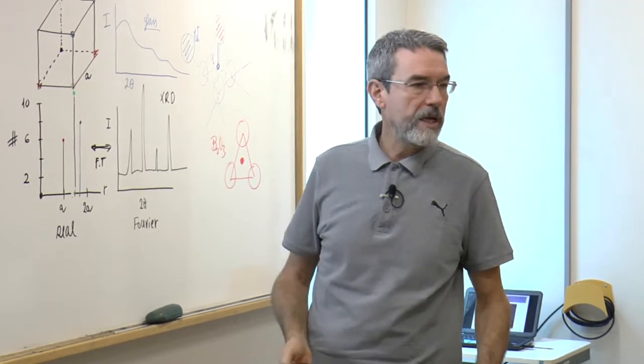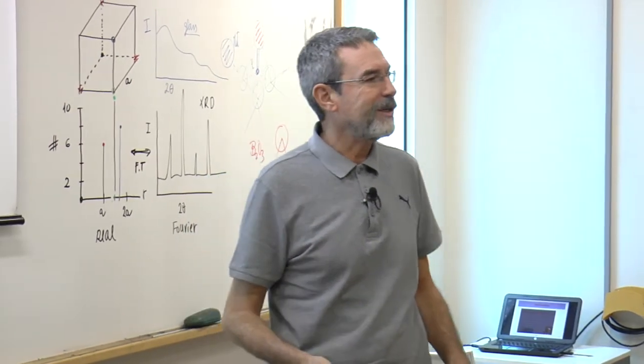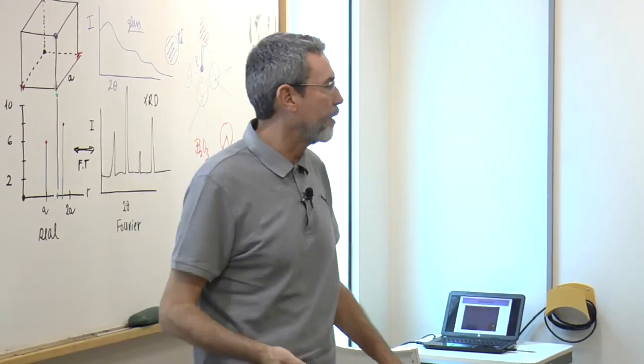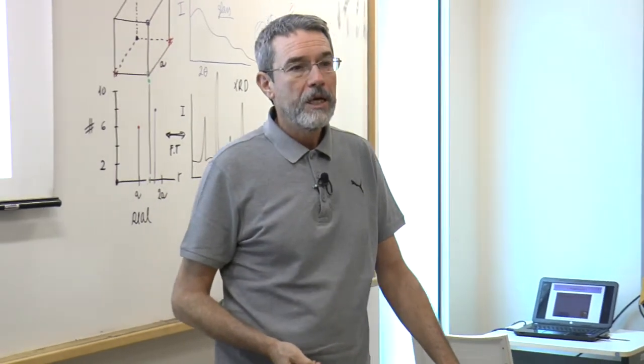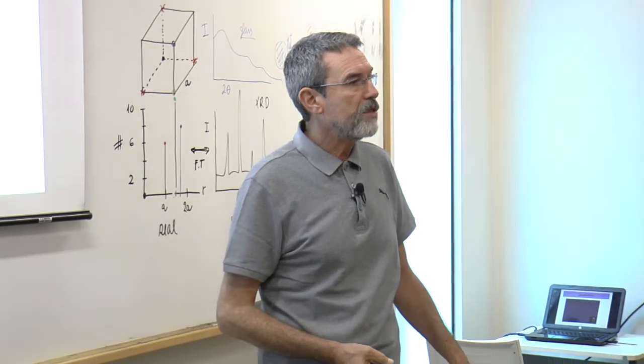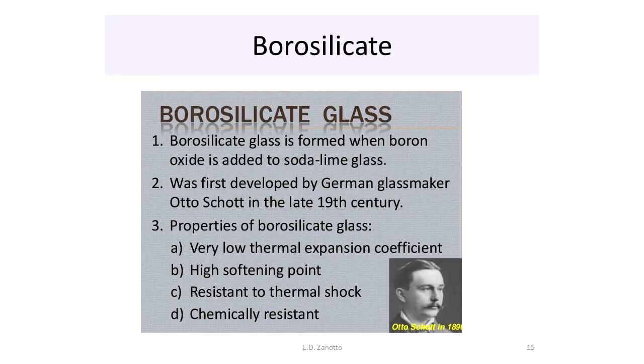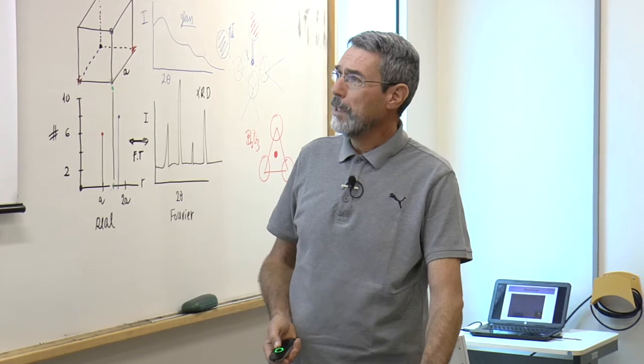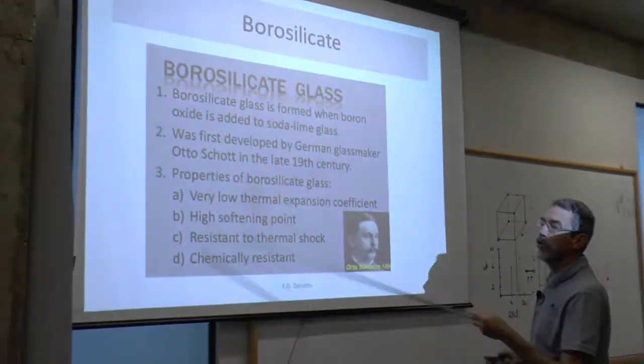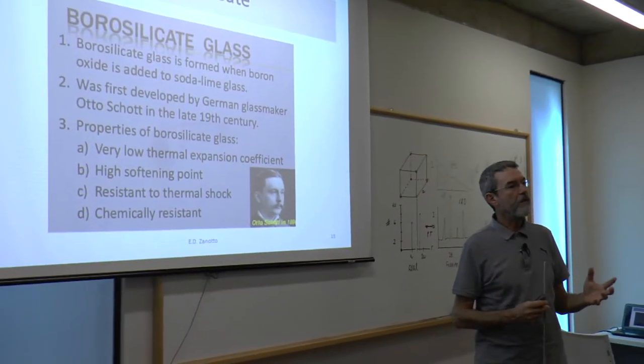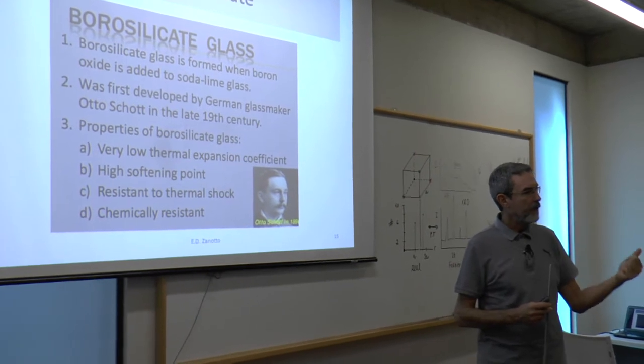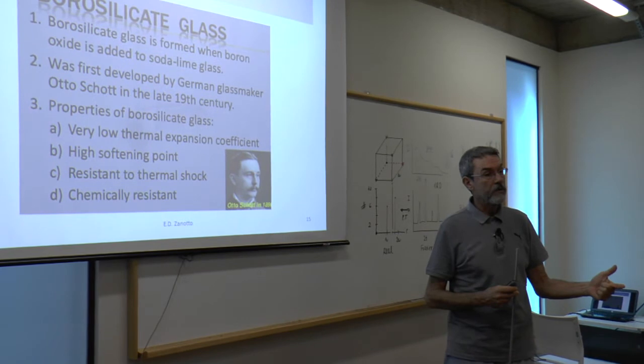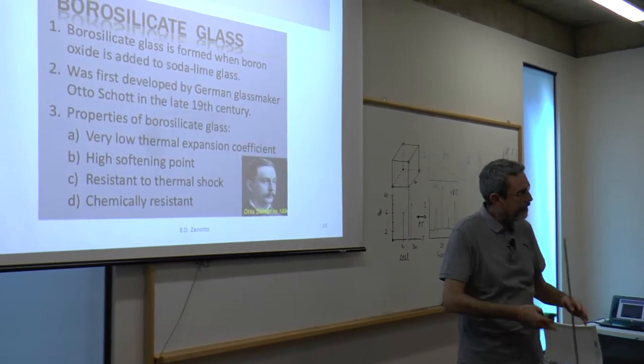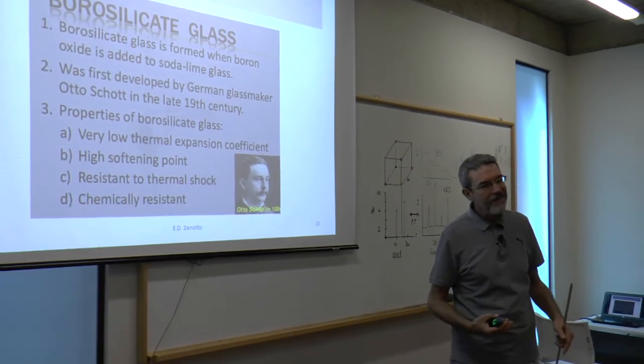Very well-known glasses, borosilicate. Trade name Pyrex, but there are other trade names. Borosilicate is very much used in laboratory, for instance, because it has very low thermal expansion coefficient, so it does not suffer much from thermal shock. It has a very high chemical durability and low density and other interesting properties that make borosilicate glass an important glass. But here we have already borosilicates, two glass forming oxides, B2O3 and SiO2. And also sodium and other oxides that are added in alumina to improve other properties. So how is the structure of these glasses?